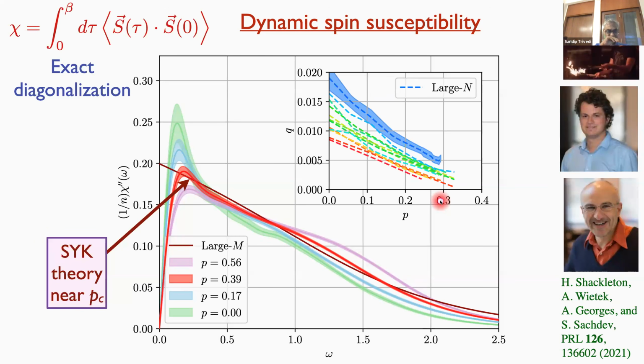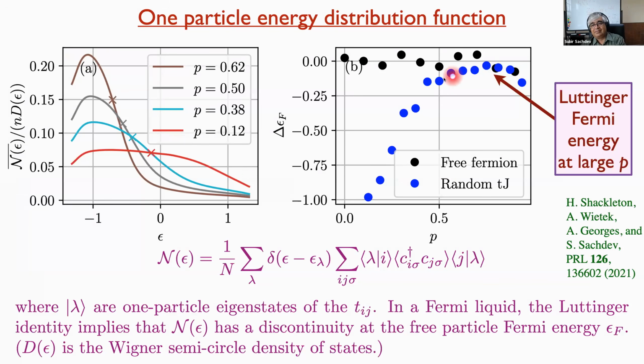But yeah, so this is pretty exciting to see this without any large M limit, where M refers to SU(M), as I'll explain in a minute. So you see this kind of SYK-like behavior, not just the leading step discontinuity, which is the 1/tau decay, but also the subleading term. This is the Fermi energy, as I was saying, and what you find is that when the blue and the black dots are the same, then the Luttinger theorem is obeyed. So let me just say that without explaining it. And it seems to be, again, until around 0.4, it's obeyed, and then it's not obeyed when you presumably enter the spin glass phase.